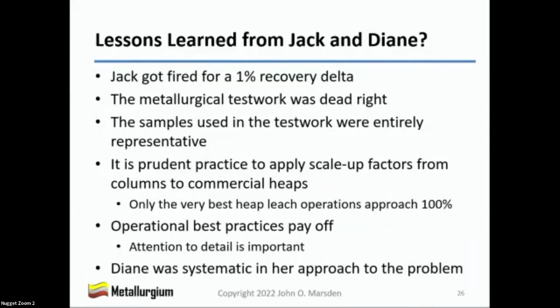So what did we learn from Jack and Diane part 1? First of all, we learned that Jack got fired for a 1% recovery delta. We learned that the test work done by McCaffrey's and Associates was dead right. They did a great job. We learned that the samples used for the test work were representative. We learned that you really need to apply a prudent scale-up factor to go from columns to commercial heaps. We learned that operational best practices pay off. Everybody in this room knows that. But Diane was systematic in her approach, and she was able to problem solve and figure out how to move forward at Cherokee Creek.